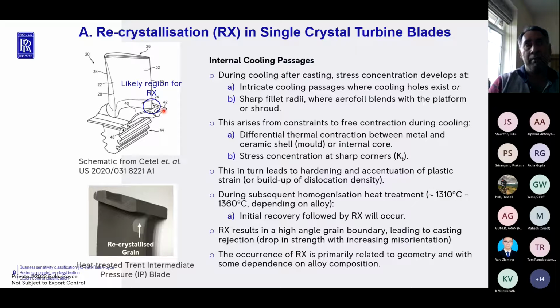But like I said, because the casting is heavily segregated, you need to homogenize it, and the typical homogenization is at very high temperatures. If you look at, like I said, we use CMSX4 and RR3010 or RR3000, the typical solutioning or homogenization temperatures vary between 1310 to 1360 depending on the alloy. And the typical isothermal hold at these temperatures could be anything between 5 to 20 hours.